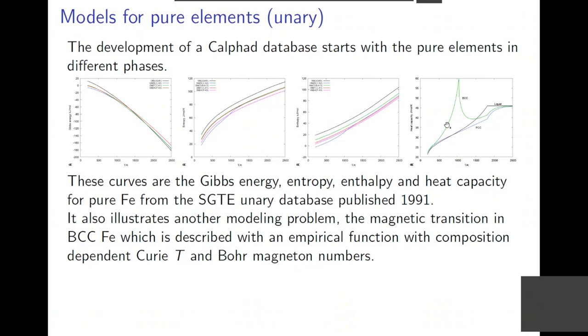What was done in 1991 with the SGTE unary database was adding heat capacity data to the lattice stabilities. But that included also a magnetic model. So one separated out the contribution from the ferromagnetic transition in an empirical model, which depended on the Curie temperature and the Bohr magneton numbers.